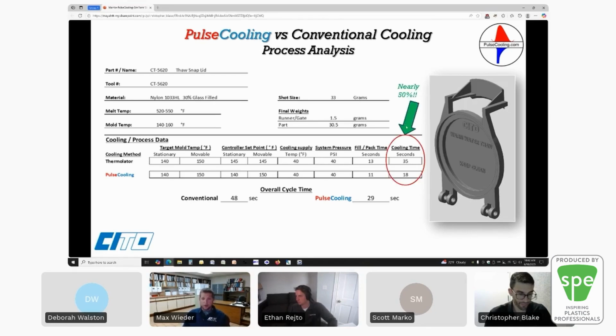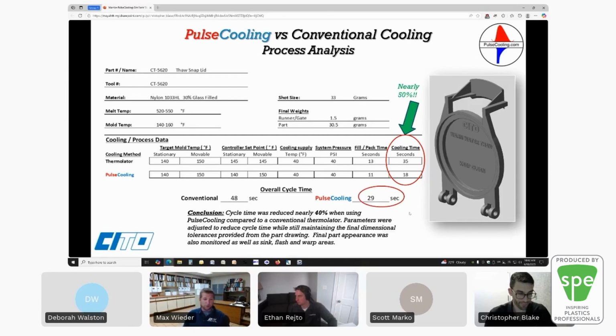With that, we saw nearly 50% reduction in cooling time, which resulted in a cycle time reduction of nearly 40% when using pulse cooling compared to conventional thermalator cooling. This was all achieved while still maintaining final dimensions and part appearance.